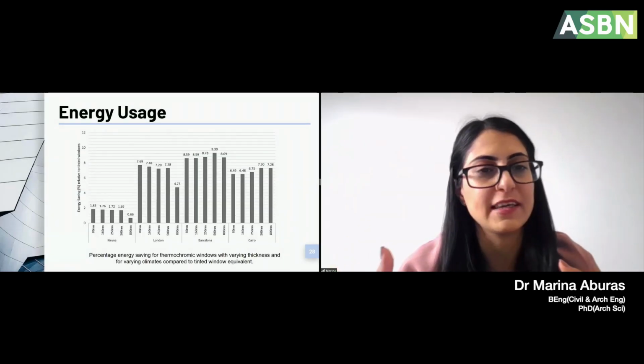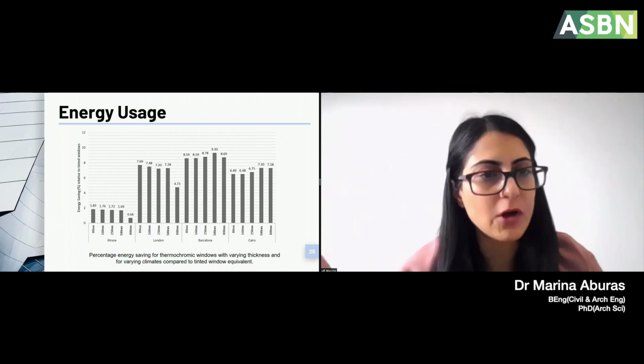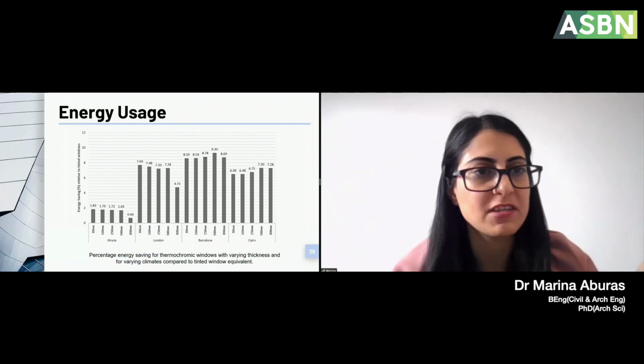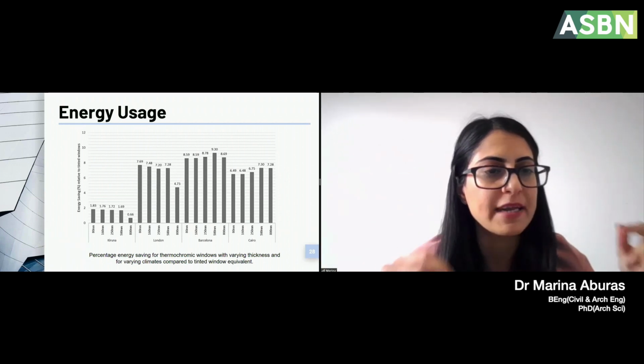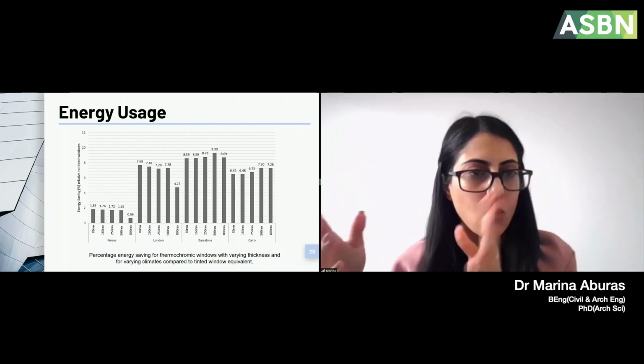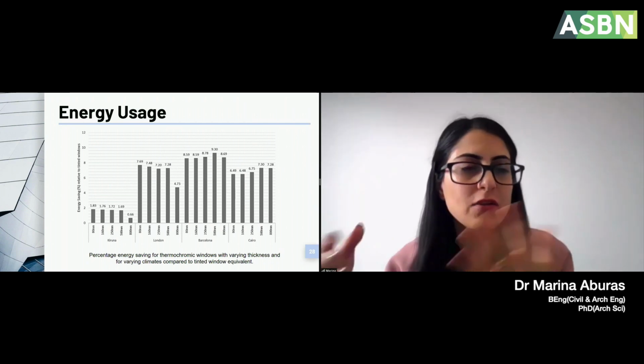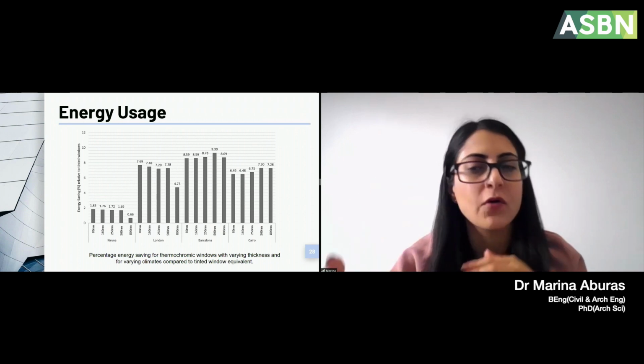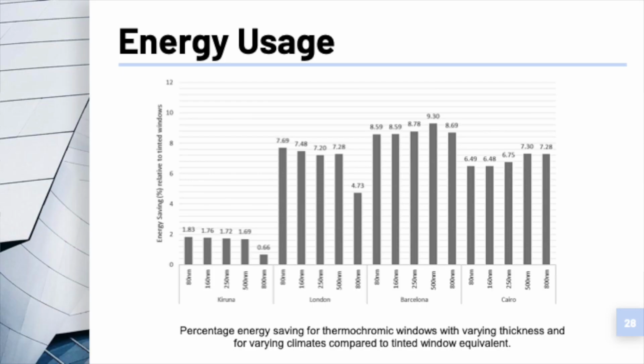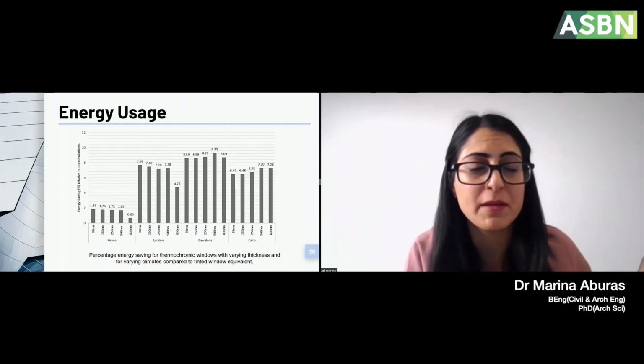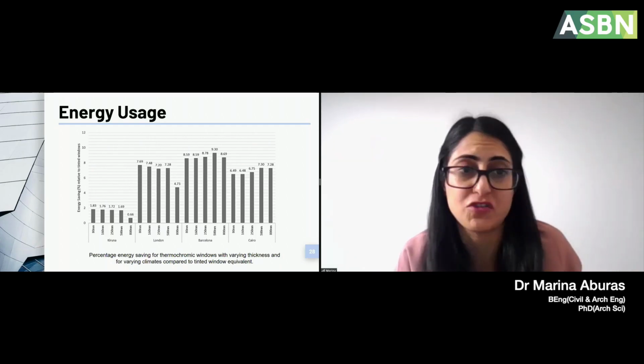And where it got really interesting is where we then went, hang on, these coatings that are getting thicker are also getting darker. What happens if you compare their benefit not against a double glazed window, but against a tinted window equivalent, where you actually hold the visible component steady, so that you're really comparing against what would happen with the thermochromic window versus the tint alone. And this was interesting because you could see that you still get more energy saving for the thicker coatings in the warmer climates, but in the cooler climates, that's not the case, where for a thicker coating, you have less energy saving relative to a tinted window, which just translates to mean for those climates, you're probably better off from a cost perspective and other perspectives just using a tinted window.